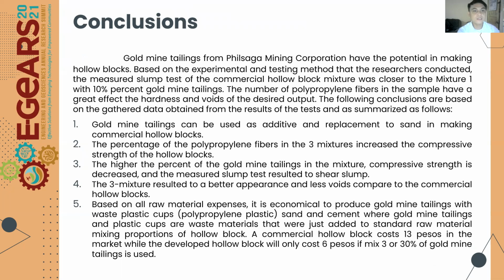Conclusion. Gold mine tailings from Philsaga Mining Corporation have potential in making hollow blocks. Based on the experimental and testing method that the researchers conducted, the measured slump of the commercial hollow blocks mixture was close to mix 1 with 10% gold mine tailings. The number of polypropylene fibers in the sample has a great effect on the hardness and voids of the desired output.